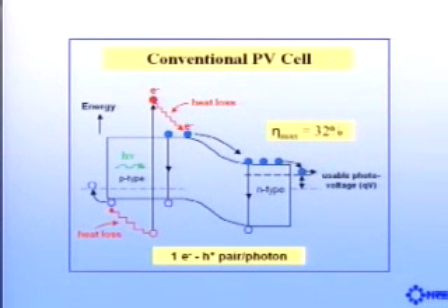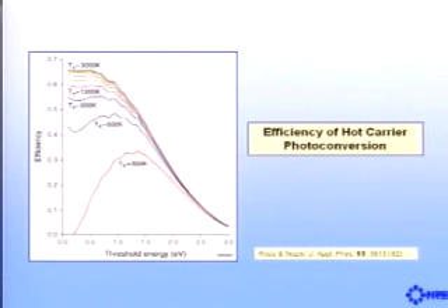Now, this has been a good assumption until recently because this process is very fast in bulk semiconductors. It occurs on a sub-picosecond time scale, probably 10 to the minus 13 seconds. And so that's how you get the 32%. You assume all the electrons and holes equilibrate very rapidly, and you can't utilize that extra energy. Now, over 20 years ago, we showed that if you could use those carriers at the energy at which they were created, you could more than double the efficiency. This is the electron temperature. You could assign a temperature to the electrons if they equilibrate with each other. And it's the same value that you would get if you had an infinite stack of band gaps matched to the solar spectrum. Thermodynamically, you have the same final state.